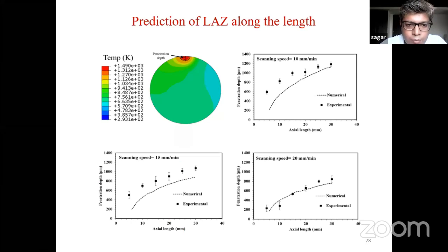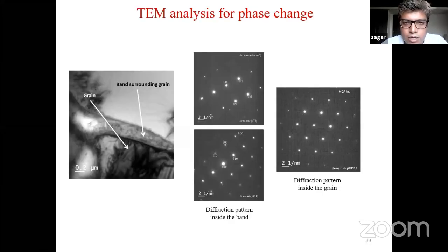We have plotted the temperature profile and seen with that temperature profile many of the phases could be predicted, like orthorhombic structure, then BCC structure. Those formations were possible. So the same has been established through TEM analysis. So this is nothing but the validation of that phase prediction.